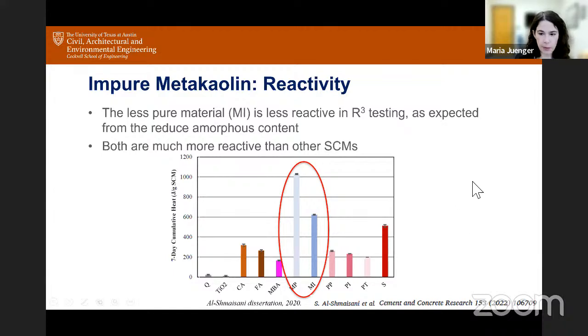The other thing that happens with this is, of course, if you reduce the purity, you reduce the reactivity. So this is the R3 test again. The MP is the pure metakaolin, and the MI is the impure metakaolin in this plot. We can see that both of these, even the impure one, are much more reactive than other SCMs. They're much more reactive than these pumices. They're much more reactive than the fly ashes. And so even when you make it less pure, you still have a greater reactivity from that material, when it's 77% amorphous.